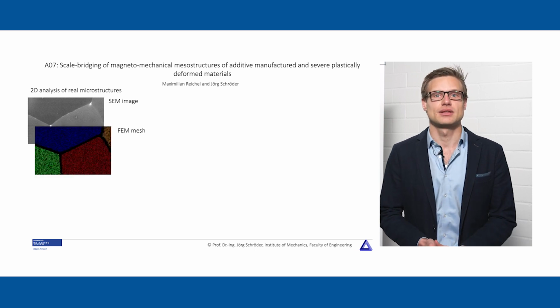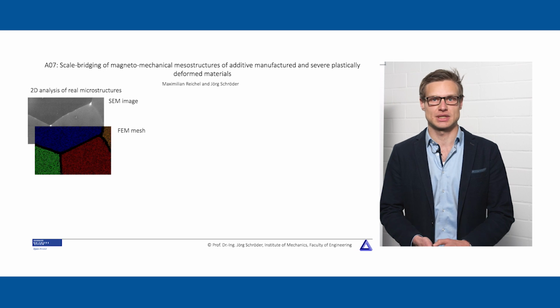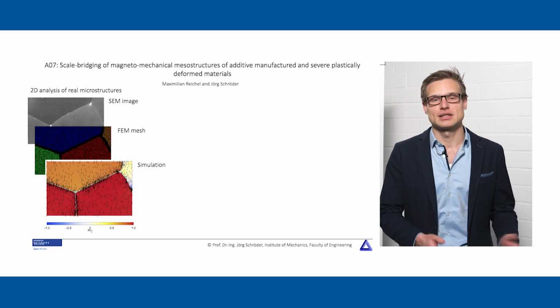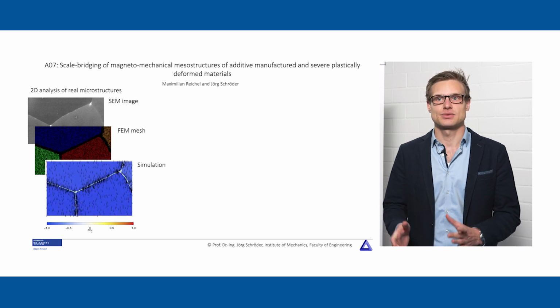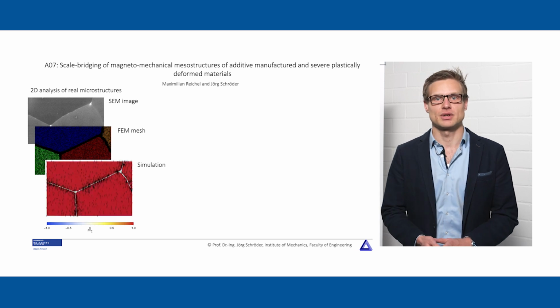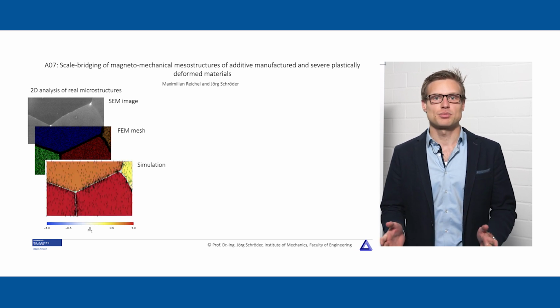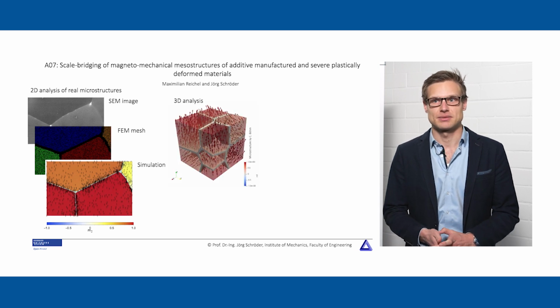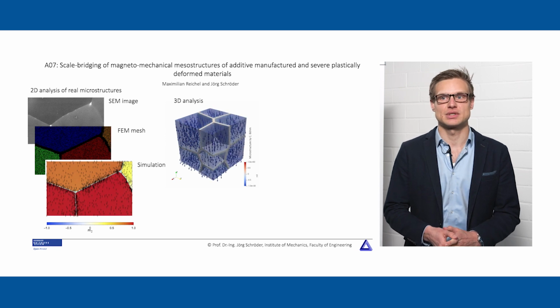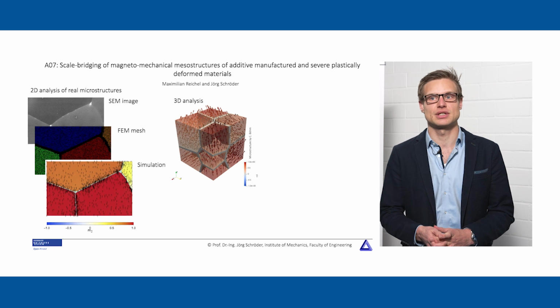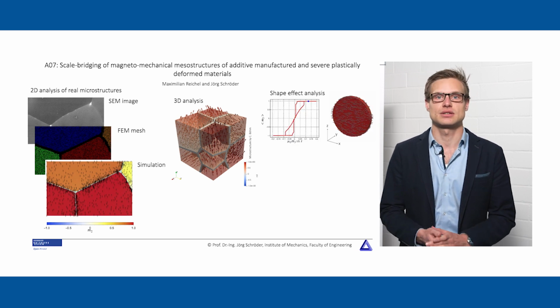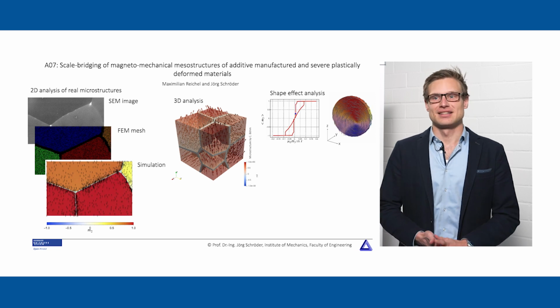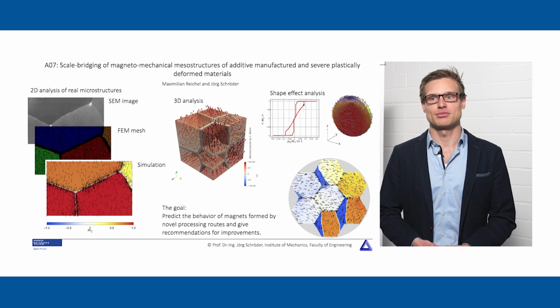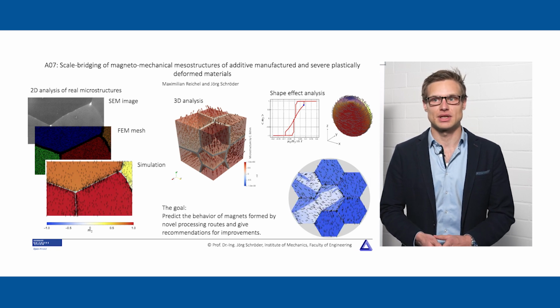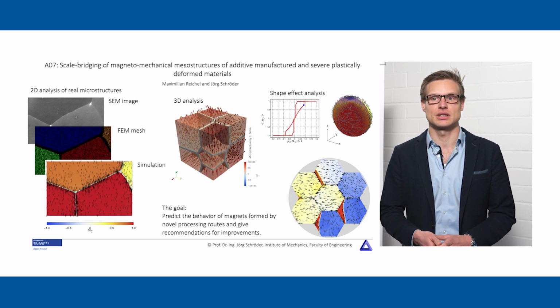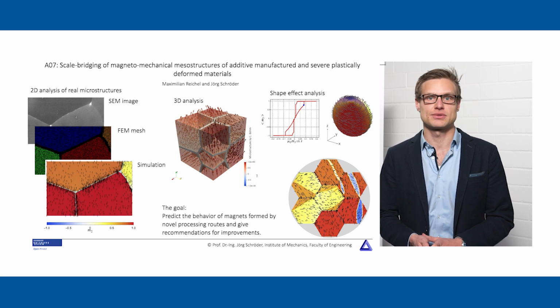To perform simulations, this microstructure needs to be transferred into a discrete counterpart. Together with the beforehand introduced system of equations and the discrete microstructure, the following simulation results can now be obtained. What is possible in 2 dimensions is also possible in 3 dimensions. As shown here, the simulation results of the magnetization reversal of an artificially generated polycrystalline microstructure or the hysteresis simulation of this nanodot. As mentioned before, the goal is to predict the behavior of magnets formed by novel processing routes, like the simulation results of a microstructure formed by rotary swaging, as shown on the right, and to give recommendations for improvements.